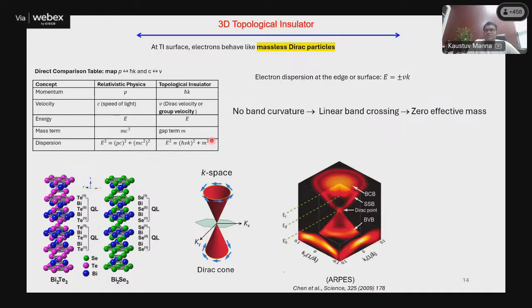Linear band crossing means if you have the expression like this, then, see, what is M? M is called the mass term. This is a magnetic component. But in a topological insulator, there is no magnetism. The time reversal symmetry is already conserved. There is no magnetism, so there is no mass term in the topological insulator. So if the mass term is zero, in that case the energy looks like this: E equals plus or minus nu times K. So plus minus K means it's a linear dispersion. If you plot E versus K, it's a linear band crossing.